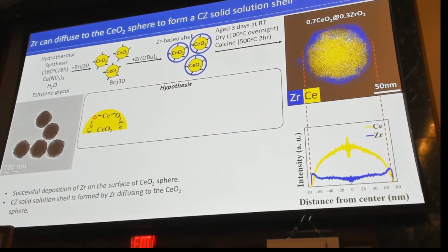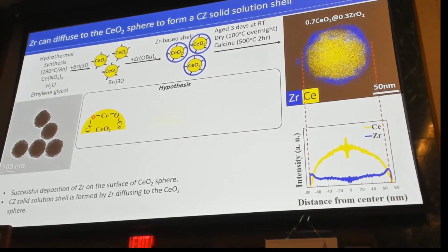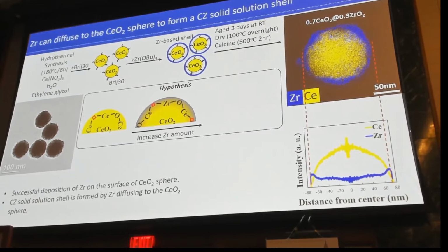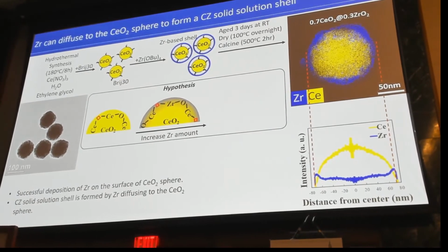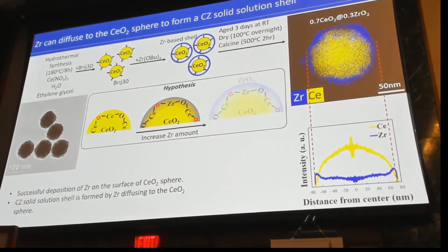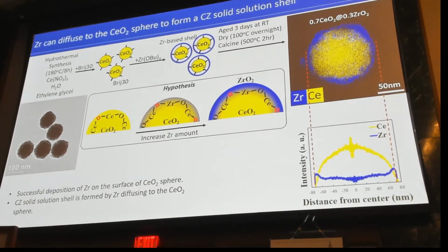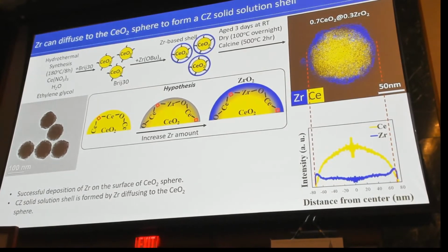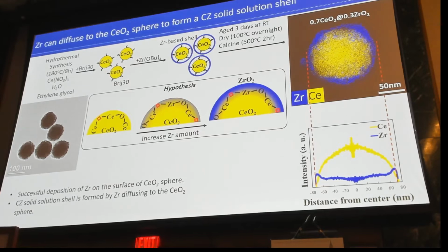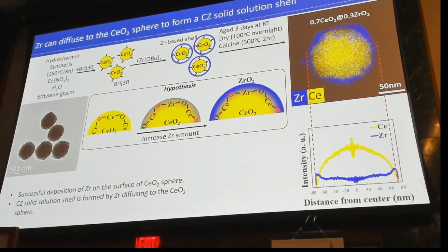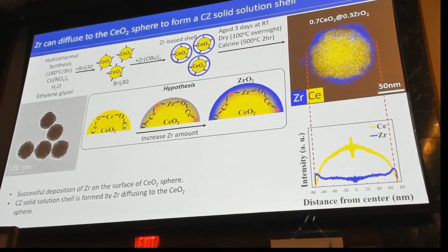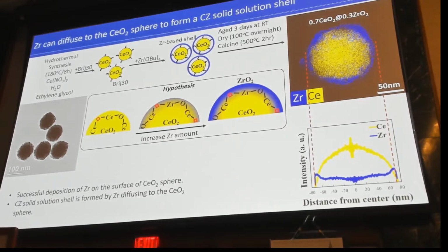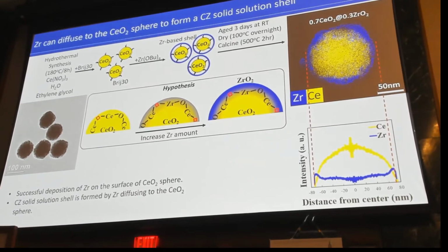So these are hypotheses. This is what happens when we have just the ceria spheres. We start adding zirconium, we start creating a solid solution of zirconium on the surface. Then we add more zirconium, and in that case we start forming crystallized zirconia. This is actually not preferred because, as I will show you later on, we have platinum in the catalyst, and platinum does not interact so strongly with crystallized zirconia and forms big particles.